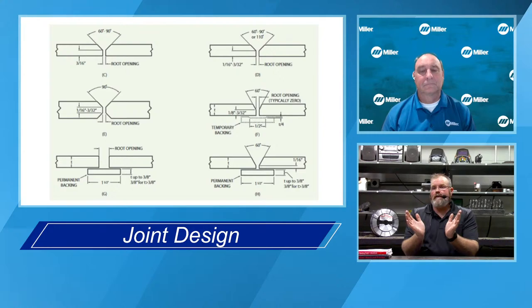When we're running aluminum on MIG out there, we control our heat through wire feed speed. We just talked about that. There's so much heat sinking in aluminum. To get that heat up, we're running a lot of wire feed speed. You have to have a place for that wire to go. And so you need to open up those joint angles. So it's not uncommon to start seeing joint angles when we're talking aluminum getting up to 60-degree openings or even